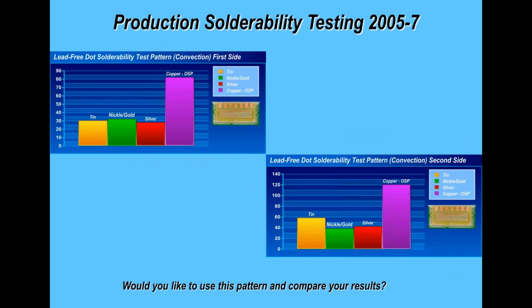So generally speaking, if you were to look at all solder finishes, if you were to do this experiment, the best performance would be a solder coating first of all, then probably nickel gold, then silver, tin, and then copper OSP. So again, it just highlights the importance of explicitly selecting the right solder finish for your particular application.